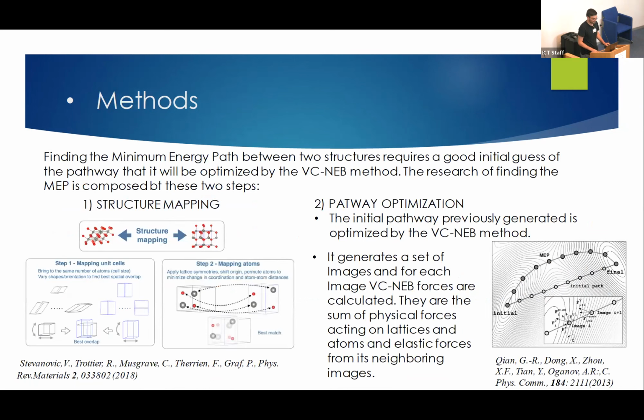And evaluating the lifetime of metastable structures requires finding the minimum energy path, but determining the best minimum energy path is quite difficult. So we use these two methods, the structure mapping and the pathway optimization, to define the best path which matches the two structures, the endpoints. And the structure mapping algorithm finds the best mapping between the two structures. So it aims to find the best overlap between the unit cells and to find the best mapping between atoms, minimizing the distances in real space of atoms and the dissociation of chemical bonds.